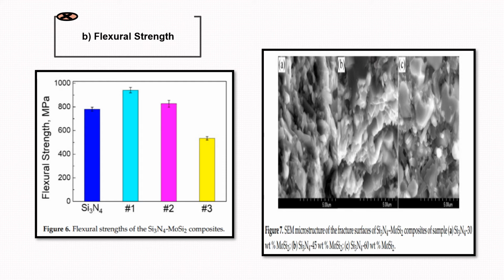Figure 7 shows the scanning electron microscopy morphology of the silicon nitride molybdenum disilicide composites. As demonstrated in this figure, the fracture of the composites was a typical intergranular fracture. The grains of the silicon nitride were rod-shaped and the grains of the molybdenum disilicide were equiaxial. In sample number 1, the grain size of the molybdenum disilicide was relatively small with a size of about 3 to 5 micrometers. An increase of molybdenum disilicide content makes the grain size of the molybdenum disilicide keep increasing slightly, and small amounts of randomly distributed rod-shaped silicon nitride crystals were observed among the molybdenum disilicide crystals.